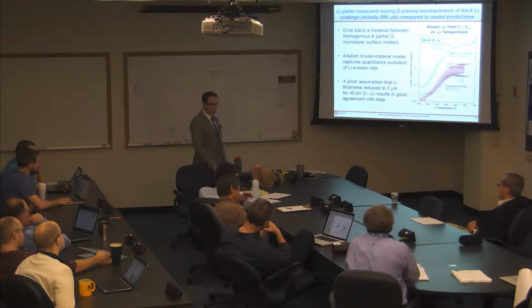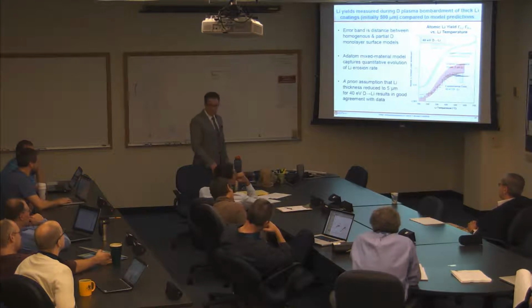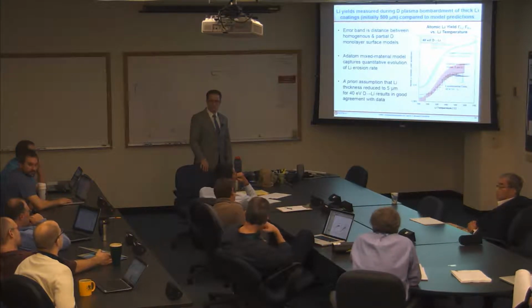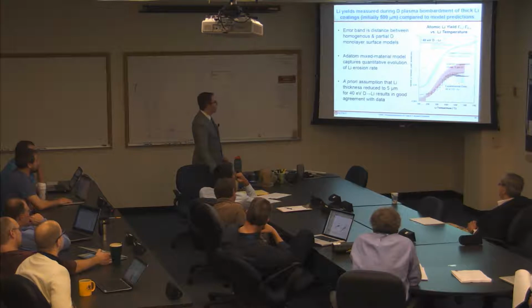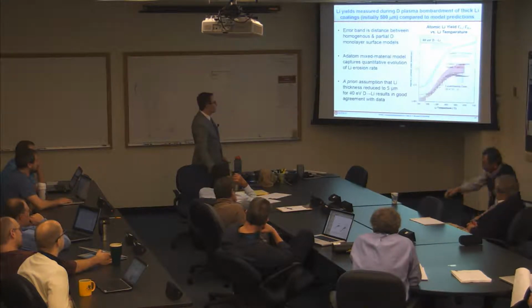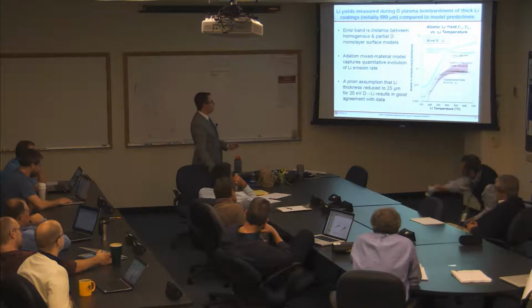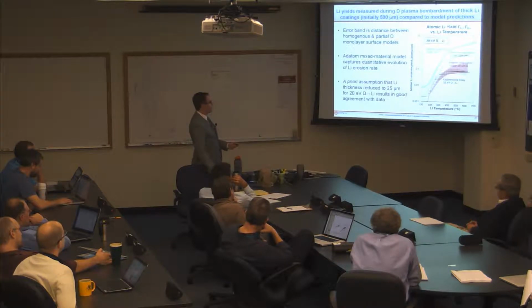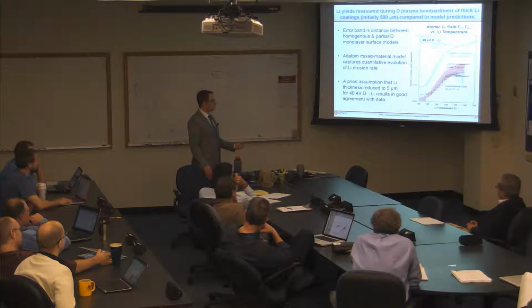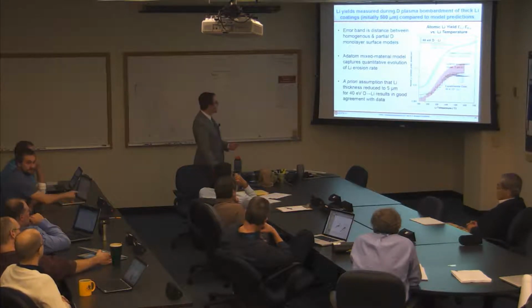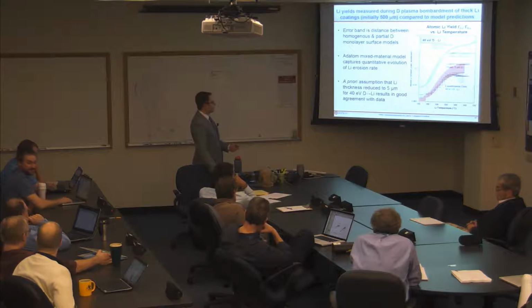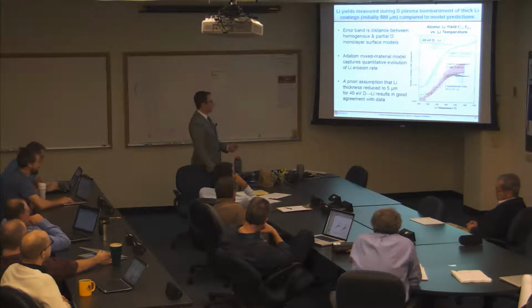Why doesn't the collisional level change in the beta equals 0 case between 20 eV and 40 eV? It doesn't? Yeah, you're right. You know what? I probably forgot to change this for the 40 eV case. Sorry. But the temperature dependent term is assumed to be independent of ion.